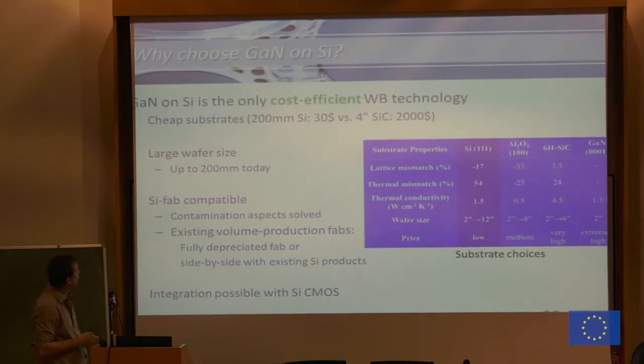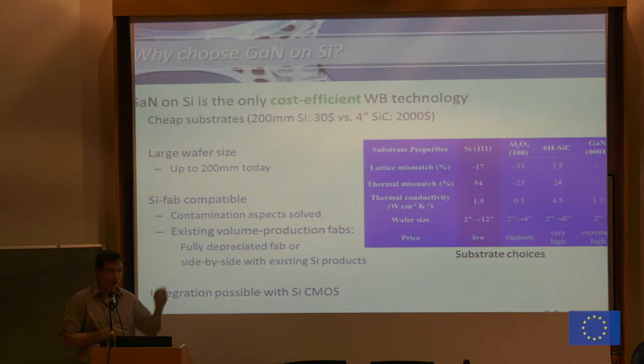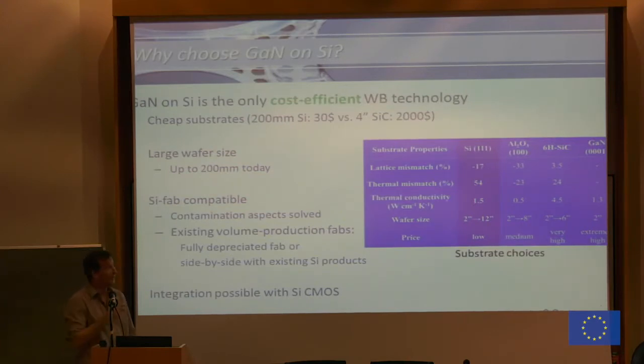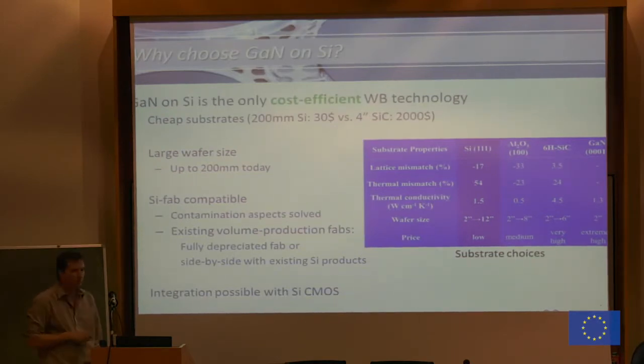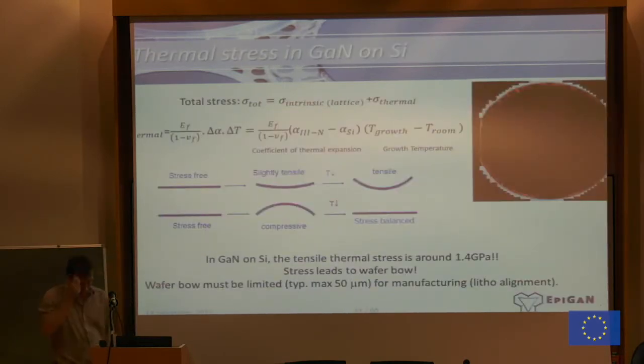I have listed here the advantages of gallium nitride on silicon. For instance, here you see the difference in cost. A 4-inch silicon carbide substrate costs $2,000, substrate alone, you have not done any epi on top of it. A 200 millimeter silicon is $30. So that gives you the range of the cost. Also important is that silicon is something that people that have a background in silicon electronics are more willing to accept into their fab because they're used to that material. And probably something that will be important in the future is that if you work on silicon, you open up a whole range of integration possibilities with silicon, something that you don't have if you work, for instance, on silicon carbide. Now, growing on silicon has one additional disadvantage.